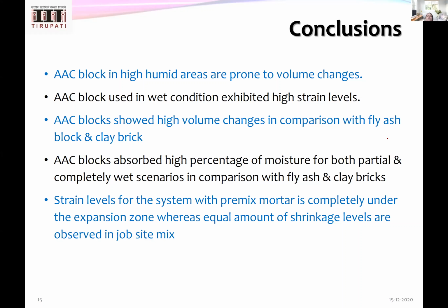But for us, with an AAC block as an infill wall, moisture change is the main reason regarding the crack in the system, which is actually caused because we have a system where we are not allowing the free expansion of the bricks. Obviously, it will create restraint in the system and cracks will happen. And free expansion for an infill wall is not so easy to provide. Even if you're providing free expansion at the end of 6 meter or 10 meter, sometimes it may not be sufficient because you will have bricks which come inside, which will create a restraint in the system.